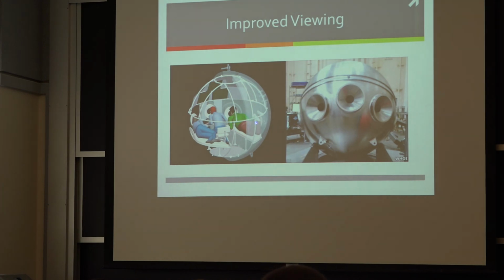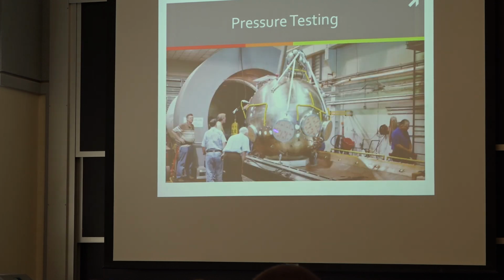So here's the sphere, with better ergonomics inside with the viewing ports, and here's the sphere with 5 viewing ports. You can see 2 on the side, 3 in the middle. Here, and I believe this is probably a Carderock, here's the sphere going under in its pressure test. It's about, I don't remember, a little over 7 feet in diameter. This chamber is just a little over 8 feet in diameter because I believe this chamber was built for the Sea Cliff to do the qualification of the Sea Cliff, which was a Navy vessel.